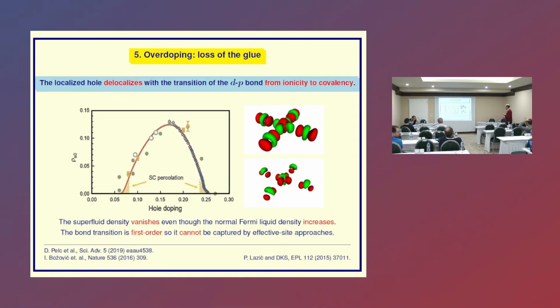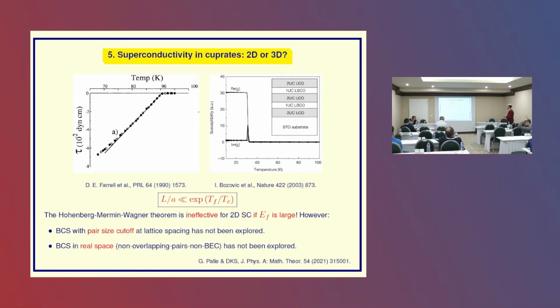And here you have a covalent situation like any three-band model without any correlations, where you just lift the Fermi energy, and then you can see that both the copper and the oxygen orbitals have acquired positive charge. In other words, they are filling coherently. Okay, this is characteristic of the covalent bond. So what we have here is that we transition from an ionic bond here to a covalent bond here, and this is the reason why the Fermi liquid density increases, but the superconducting density decreases.